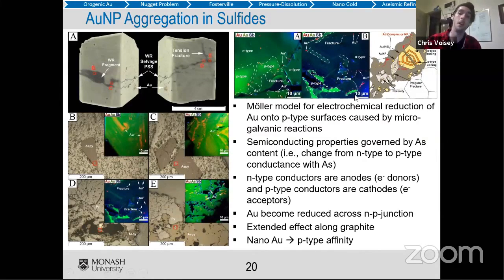This opens up a lot more if you're dealing with pressure dissolved selvages with pyrites in them. The pyrites become cataclastic. We can see that with how fractured these things are, the embayment textures, and then you're opening up more NP junctions. So instead of having, let's say, one crystal with a P-type zone in the middle, by fracturing it, you're opening it up to have fluid flow, and you can hit more NP junctions if the fluid goes through it. And this sort of electrical conductance can actually become a little bit long-ranged if it's hosted in something that's quite conductive, like a graphite seam.